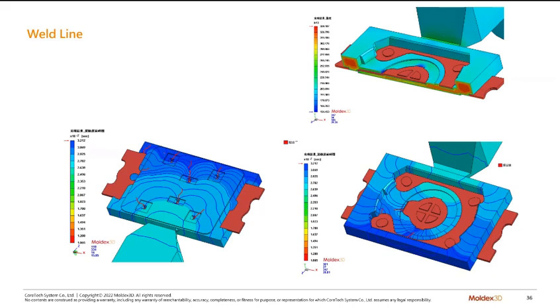Okay, for sure they have weld issues, and if the gates are here, you can imagine that the melt front will go these directions because there are sink features here, so the material will go very slowly in these features, and when those melt fronts meet here to create the weld lines, the quality of the weld line will be very, very bad because the temperature of the melt front will be very, very low when they meet each other. And it might be the reason they have the crack, because of the poor quality of the weld line.